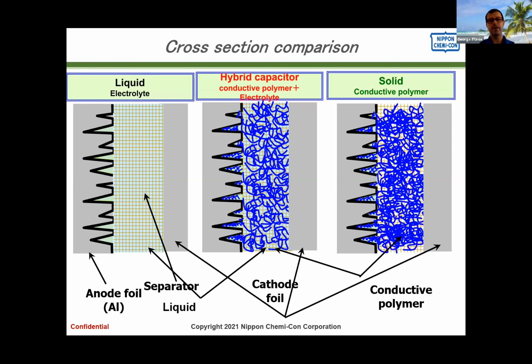When you're talking about a liquid type of capacitor or a hybrid capacitor, the separator provides the storage area for the liquid electrolyte. So of course, it has to be able to prevent physical contact between the two foils, but it also has to be able to hold the electrolyte and allow migration of the electrolyte from the separator to the surface of the foil. In liquid capacitors and hybrid capacitors, almost 100% of the liquid electrolyte is inside the separator. If you open up an electrolytic capacitor, there is no free liquid that you will find in there. It is not like an oil-filled film capacitor. It'll be almost dry once you open it, once you take it apart.